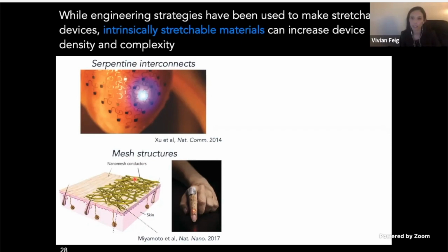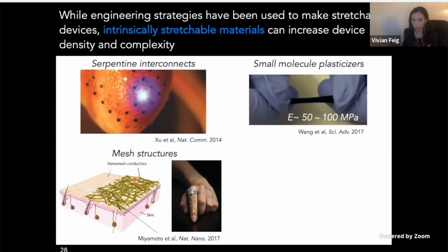And so for future electronic devices, there's been a real interest in creating intrinsically stretchable conductive materials to overcome these limitations. To that end, researchers have used strategies like plasticizing with small molecule additives to make conducting polymers pretty highly stretchable. But despite all of that, the stiffnesses of these stretchable conductors are usually on the higher end of what we want, around 100 megapascal or so.